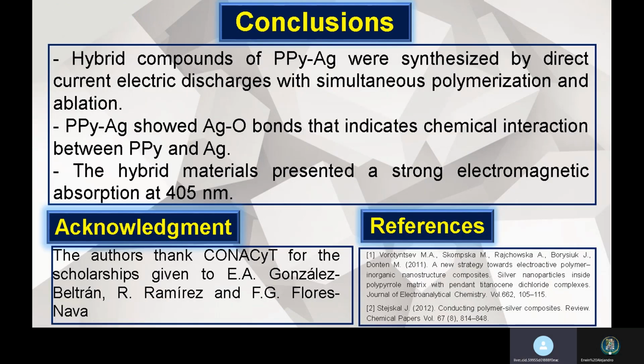As a conclusion of this project, hybrid compounds of polypyrrole and silver were synthesized by direct current electric discharges with simultaneous polymerization and ablation. Polypyrrole and silver show silver oxygen bonds that indicates chemical interaction between polypyrrole and silver. The hybrid compounds presented a strong electromagnetic absorption at 405 nanometers.